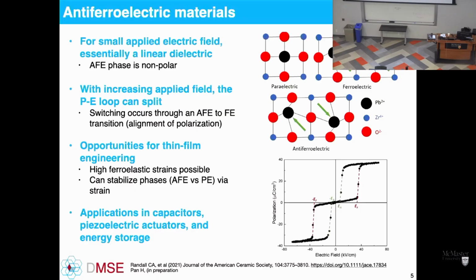And so if you look at a polarization versus electric field loop, what you'll find is that for these anti-ferroelectrics, you get a conversion from a linear dielectric, and as you apply higher and higher field, suddenly it changes. You have the net polarization, and it behaves as a ferroelectric within each quadrant of that PE loop. What this gives rise to, as we'll see, are very large strains, and there are a lot of opportunities for